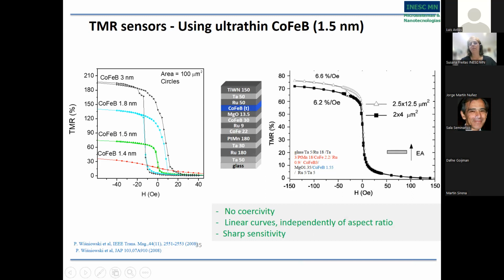And here we have an amazing high sensitivity for the sensors in magnetic tunnel junctions with MgO barriers. We can just change from a square response to a very sharp response simply by reducing the thickness of the free layer. This is the same for any magnetic material: if you have a thick magnetic material, it becomes like a ferromagnet. So this is what we see here in the left curves. It has a squarish-like curve, it has a hysteresis.